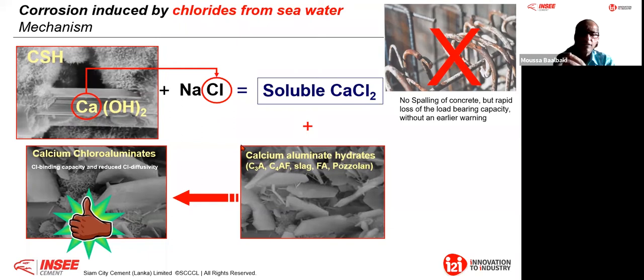Therefore, sulfate resistance is only for chemical attack due to ettringite formation. But you can use sulfate resistance based on aluminosilicate like INSE extra, that is sulfate resistant, but not OPC, rather blended hydraulic cement. And soon you will see sulfate-resistant Portland composite cement, because you have aluminate in that cement that will combine with the chloride to form calcium chloroaluminate. We call this Friedel's salt. Scientifically, that's what we call it. Therefore, that is one of the main reasons here.